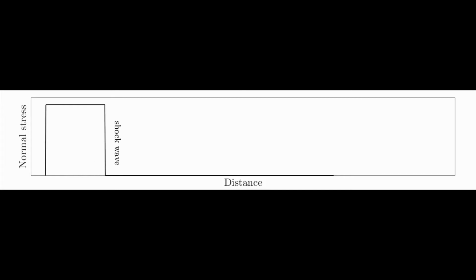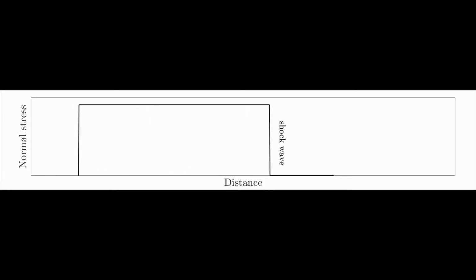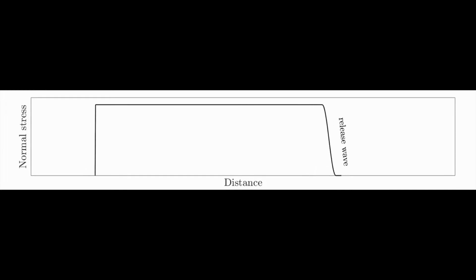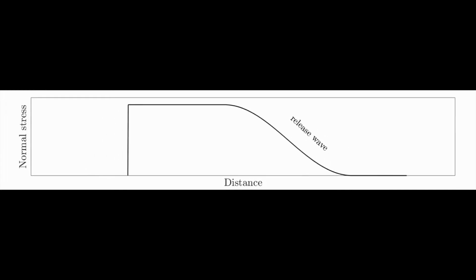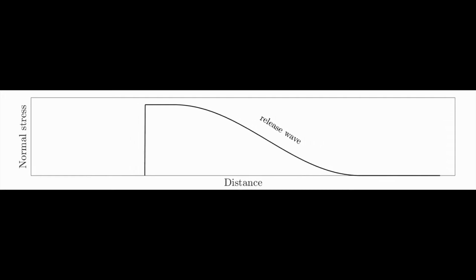shock. Consequently, a rarefaction wave is launched back into the sample that gradually allows it to release back to ambient conditions. Obviously, the conspicuous feature of a release fan is that it gradually broadens with time, unlike a shock, and so the release rate falls as one moves further away from the rear surface.